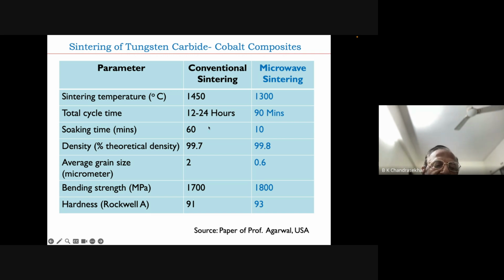And the density that we get is of the order of 99.7, provided we use cobalt as one of the materials inside, because it's a composite of tungsten carbide and cobalt. The higher the density, the better the properties of the tungsten carbide tool.